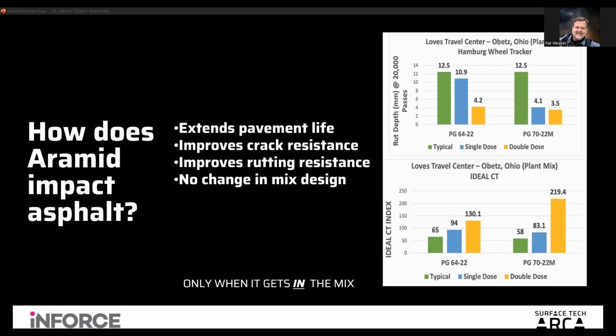And just to the right, we're not going to camp on those test results, but this is just one project where we put a wheel tracker on two different mixes on the same project. When you introduce the fiber in single doses and double doses, depending on what we are looking to accomplish with equivalent single axle loads, sometimes we'll use more than a single dose. We'll double dose it, or use a 1 1/4 dose, or 1 1/2 dose. There's a lot of different reasons I'm not going to camp on right now, but you can see we reduced the rutting over 20,000 passes significantly with different types of bitumen, and that's what this shows us.